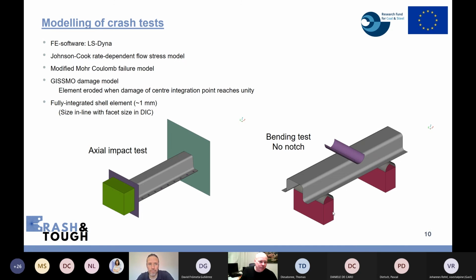At LTU, in our case, we are using LS-DYNA. Once again, we have a Johnson-Cook rate-dependent flow stress model. We have a modified Mohr-Coulomb failure model. We have this GISSMO damage model, and the element will be eroded when the damage of the central integration point reaches unity. We have used fully integrated shell elements of size 1 millimeter, and this size is correlated to the size we have with the facets in the DIC for the stepwise modeling method. So we detect the fracture strain with the same size as these shell elements.